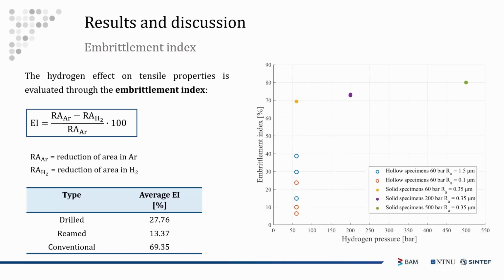Regarding the results we have obtained after this testing campaign, we evaluated the impact of hydrogen on the tensile properties using a well-known index that is known as embrittlement index. It is defined as the ratio between the reduction of area measured in reference environment. In this case, we used argon in the case of hollow specimens and air for the tests in autoclave, minus the reduction of area in hydrogen divided by the reduction of area in the reference environment.